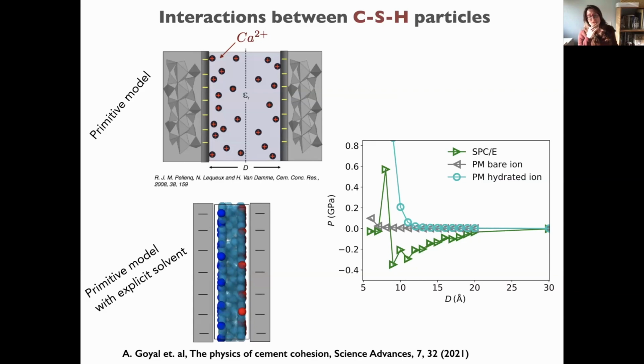The reason for this is because the primitive model accounts for point charges, whereas here we know that the ions have a size because of the hydration shell. But this is not enough to give us, at least qualitatively, the right type of interaction.